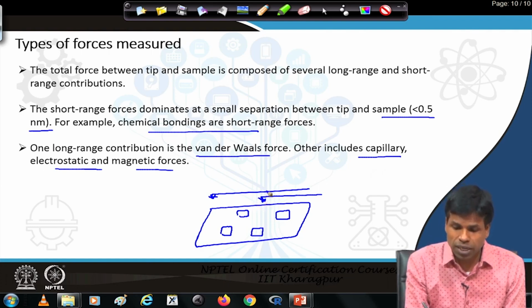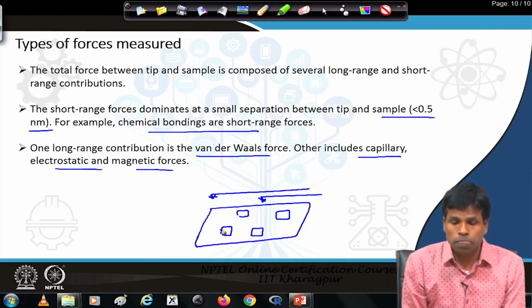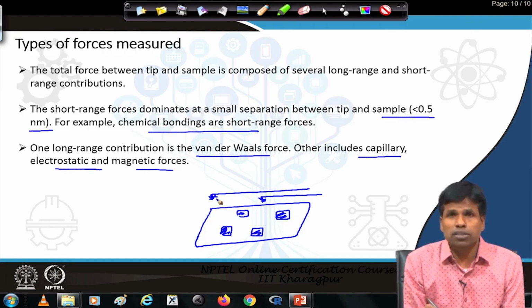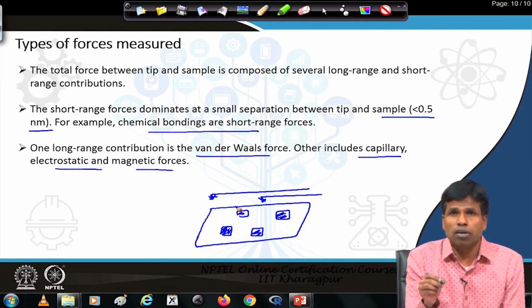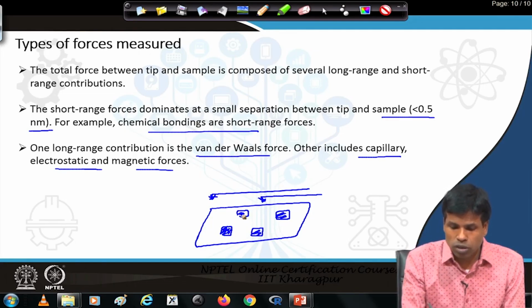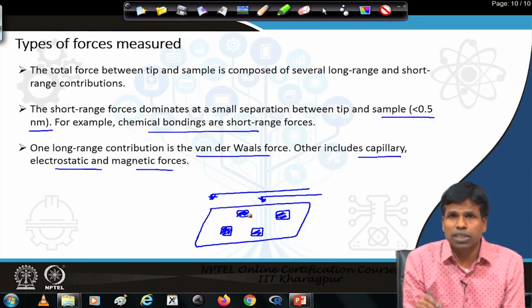If the tip has a certain magnet and your unknown material has some magnetic particles in it, then when the tip scans over the surface, it will see a different type of force, that is a magnetic force, in the region where magnetic particles are present. And here the tip does not have to come very close to the sample, because magnetic force is a long range force. Even if the tip is more than 2-3 nanometer or 5 nanometer, 10 nanometer away from the sample surface, the tip can still experience the magnetic force, and wherever the tip sees a magnetic force, we know that a magnetic particle is present in that region.